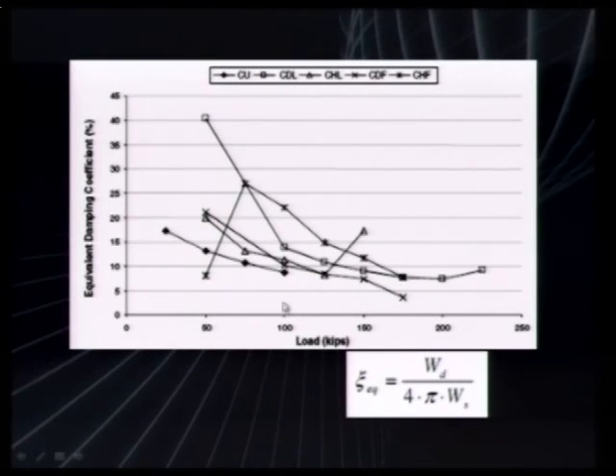In this study, when there is an increase in the load bearing capacity of the specimens, the equivalent damping coefficients decrease. It actually means that when there is less damage in the mock-ups, the wallets, we say the 1 meter by 1 meter walls as mock-ups or wallets, when they have less damage, proportionally they have less damping.